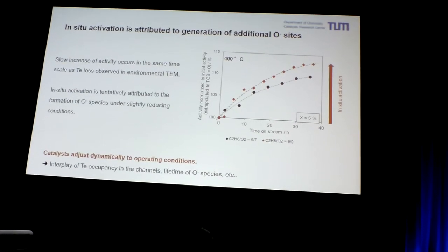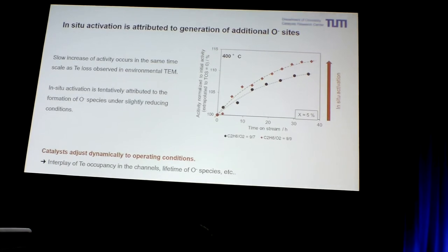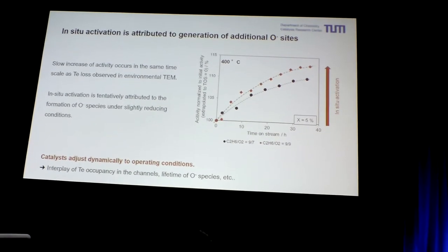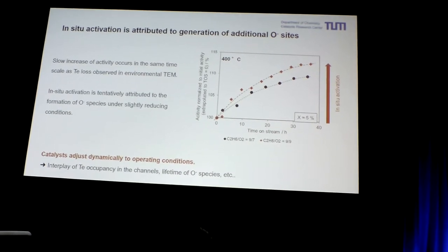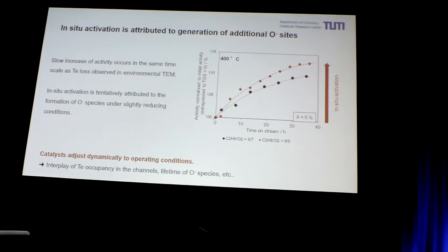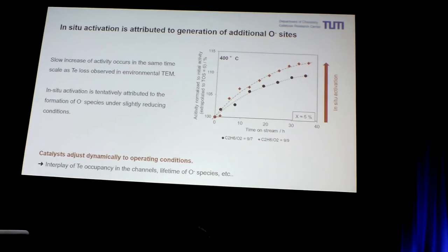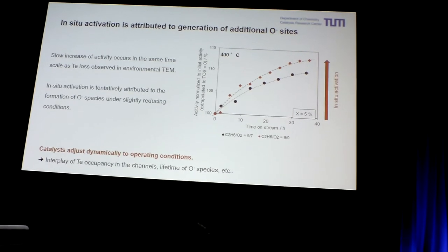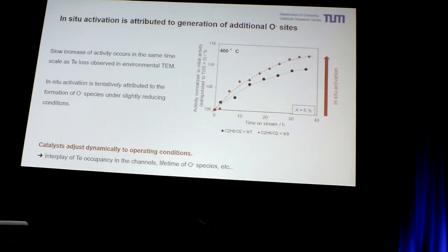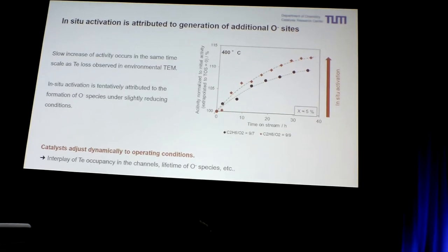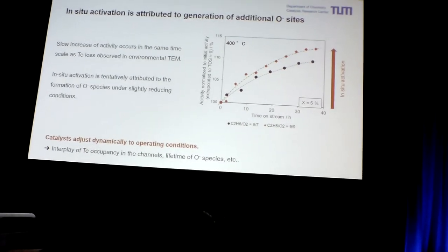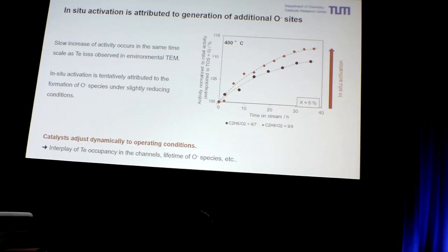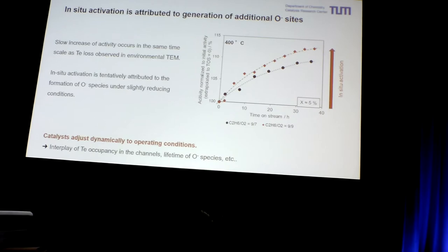So, because these observations in environmental TEM happen at the same time scale as these changes that we have observed, this in situ activation in the first hours, we attribute this additional activity that we gain in the first hours under reaction to these additional sites that, together with the vanadyl species, are on the surface of our material. So to sum up this part, we have seen how the catalysts adjust dynamically to the operating conditions.